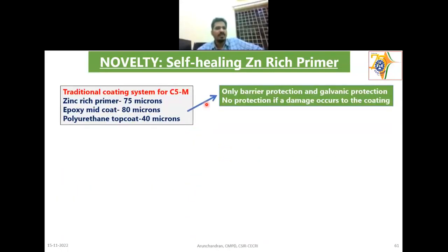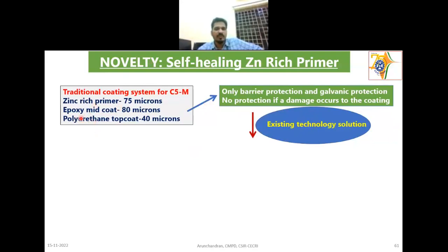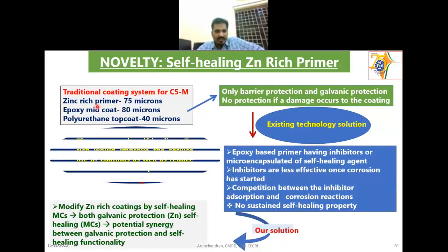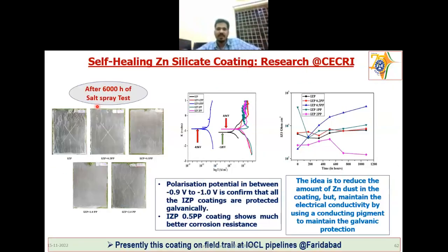So this is a typical traditional coating system. The zinc-rich primer is there. To the zinc-rich primer we are adding the Pani-based pigments and finding out how it works. I'm not going to give much detail here, but I will show some of the results now. You can see this is a salt spray test, the results of the coating after 6,000 hours of salt spray. These are the coatings with different amounts of Pani pigment added. You can see we added very little, only 2%.